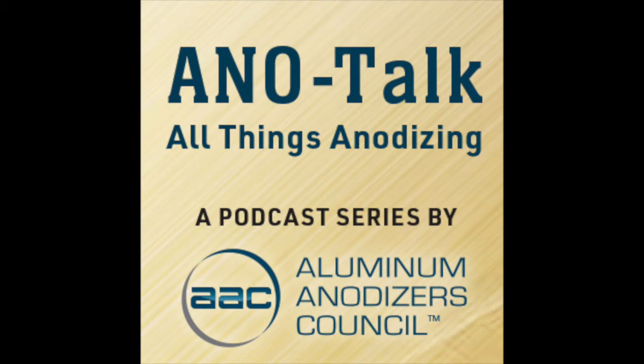Okay. So, Mark actually covered this for the most part. You've got your aluminum oxide, and if the temperature gets high, or even at lower temperatures, the sulfuric acid will dissolve the alumina. Aluminum is what's considered an amphoteric metal, so it dissolves in acids and bases, but the oxide will dissolve in acids. And like most other reactions of that sort, the higher your temperature is and the higher your concentration is, the faster your aluminum oxide will dissolve.